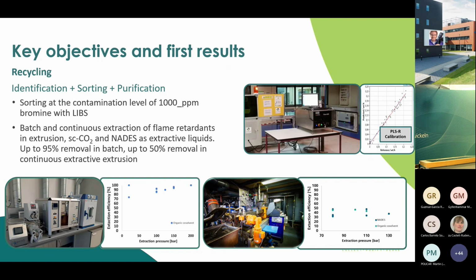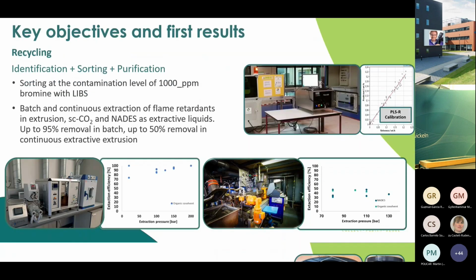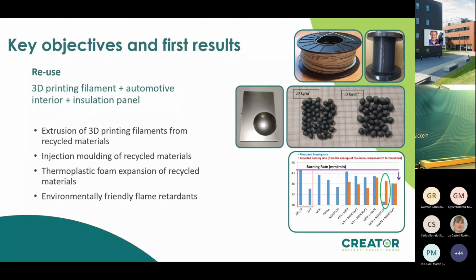And as you can see there, we don't reach the same extraction efficiency because the time, of course, in an extruder is much shorter than in a batch reactor. So at this moment, extraction efficiencies up to 50% could be obtained. For certain materials, this is sufficient to be below the 0.1% REACH legislation limit. For other materials, further optimizations would be needed, and potentially a second extrusion step will be applied to get below the limits. Of course, after the purification of the materials, the next step was the reuse.